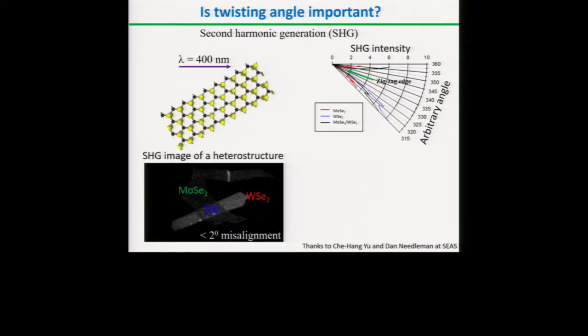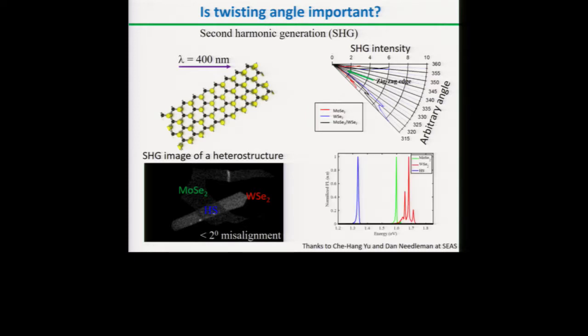So this is a second harmonic generation image of the heterostructure, where we can see tungsten selenide and MoSe2; it's a little bit dark here. And we find that the alignment is less than 2 degrees. That's where we obtain the previous data, the photoluminescence from the heterostructure, where we can see a bright interlayer exciton.